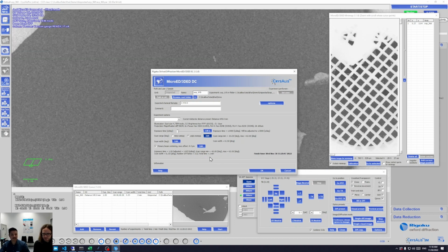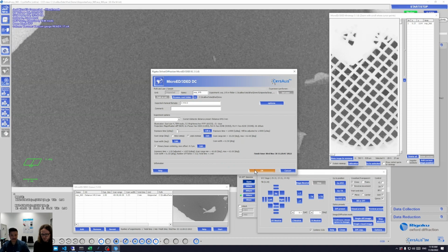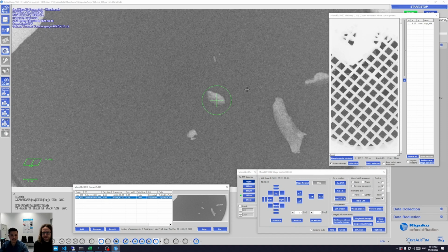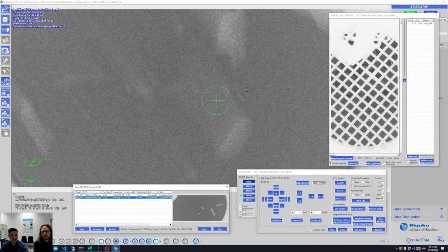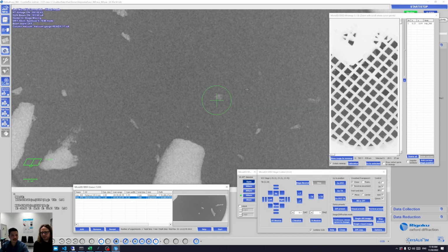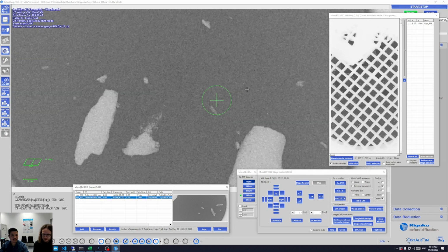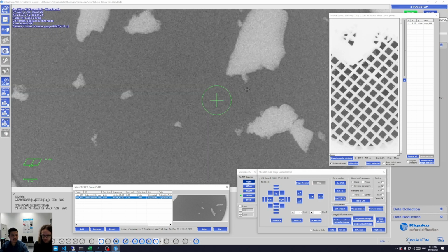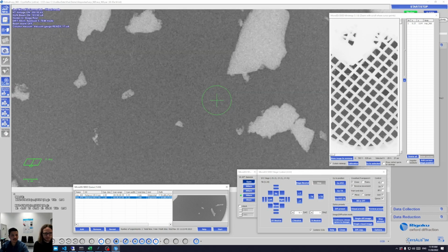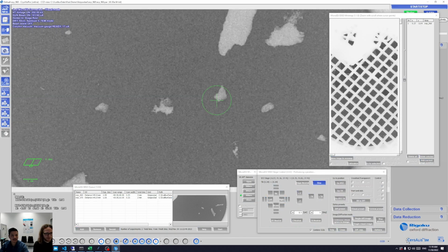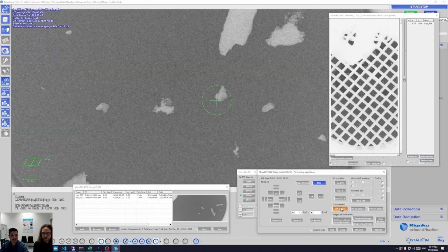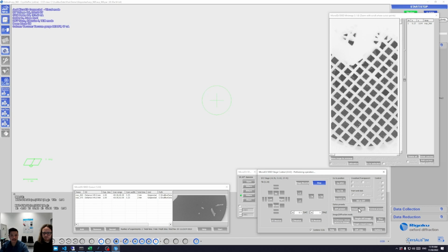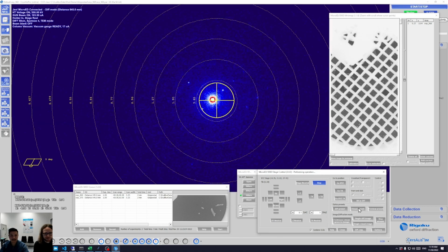The sample holder itself supports up to -80 to 80, but that depends on what specific sample holder you're using. For example, the cryo holder is -65 to 65, and generally, the more complex your holder gets, the more restricted they might be in terms of their tilting range. But all holders that we consider or recommend will at least support, let's say, -45 to 45.